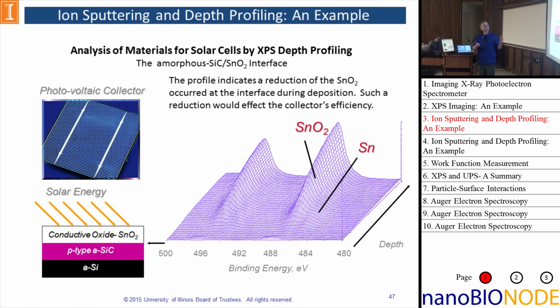So as I mentioned, in most cases the oxides are reduced, but tin oxide is one lucky case where the oxide does reduce, but it does not reduce fully to the metallic state. So I thought, I can probably do this experiment and get a result. When we sputter from the surface down to this interface right here, you can actually see a little bump develop, indicating the presence of tin metal. So this does, in fact, show that there was a little bit of reduction at the interface that carried through. And to demonstrate further that the sputtering process was not inducing this reduction, we went deeper within the tin oxide layer, and we see that eventually that bump disappears as you get into just tin oxide.